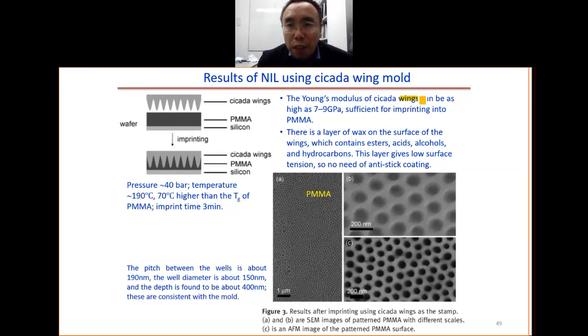But for this wing, first, it is very stable at a high temperature. Secondly, the Young's modulus is a gigapascal. It is similar to the PMMA, but here the PMMA gets melted, so it becomes soft. But this one, you get 7 to 9 gigapascal even at higher temperature. More importantly, there is a layer of wax on the wing. The wax has low surface energy, so it's easy for the separation. That means the wing naturally has an anti-sticking property.